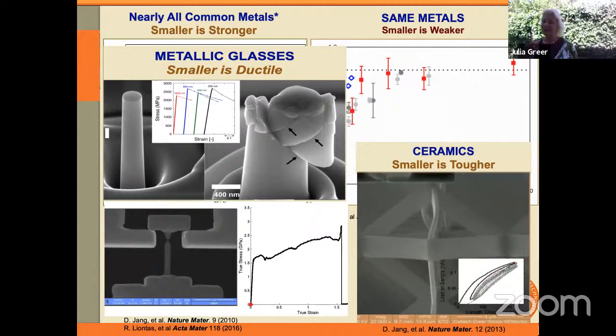Now, here's the last example of what we call the size effect, and that is we are deforming a single unit cell of one of these nanolattices. This is made out of a very brittle material, titanium nitride, and you can see that the beams are bending and deflecting, and if you were to measure the tensile stress in here, it would exceed 1.7 gigapascals. Now, something that's very brittle, when it's being tensed with a stress of 1.7 GPa should certainly not be staying intact and it would be fracturing. But you can see that these beams are able to deflect not only once, but over multiple cycles without any evidence of failure.